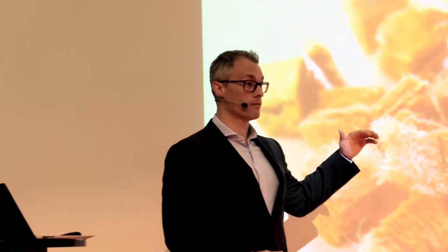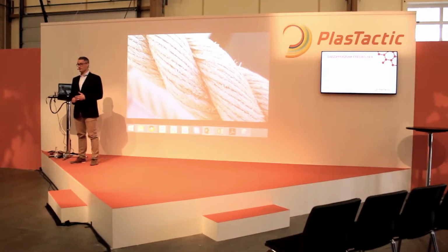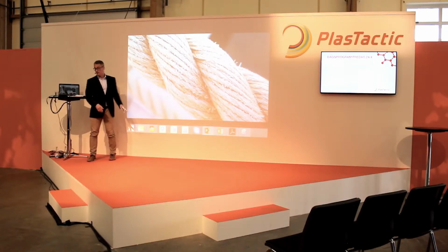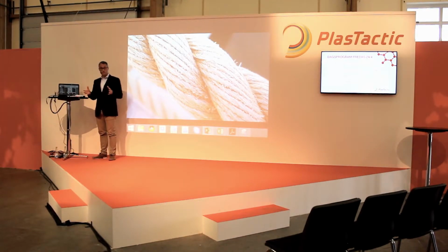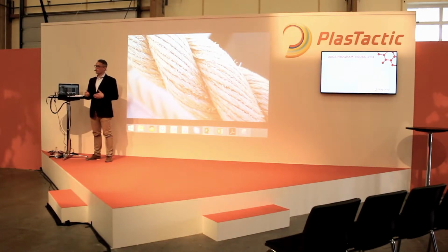So you have an excessive amount of fiber that is very, very low in weight, just sitting there. And of course, we've been using natural fibers for hundreds of years already in ropes and in other construction means. They're not as strong as synthetic fibers. They're around 800 to 1200 megapascals for hemp and flax. Glass is sitting around 2400, carbon anywhere above that.